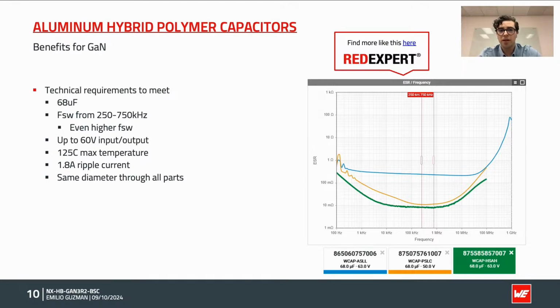And so now for the actual benefits for this design for Nexperia, some of the technical requirements that needed to meet these capacitors were 68 microfarads, a switching frequency range of 250 to 750 kilohertz, and even higher switching frequencies, up to 60 volts input-output, 125 degrees max temperature, and 1.8 amps ripple current.